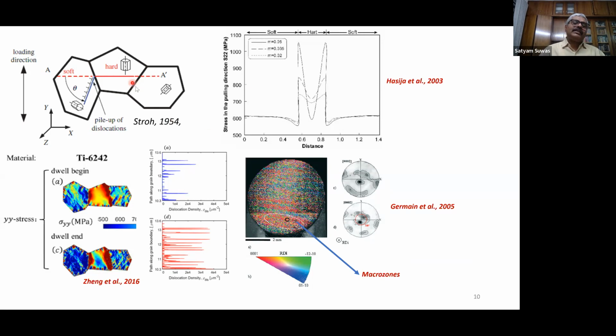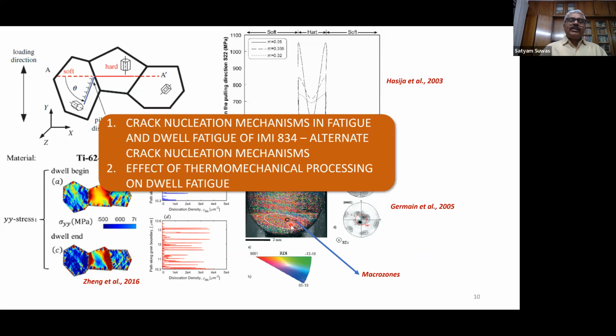So again, this validates the Stroh model: wherever there is a strong basal orientation, and it is also said that the basal grain should be surrounded by non-basal grains. In that case, there will be macrozones forming, and this could lead to a dwell fatigue debit, meaning the propensity of reducing the life under dwell fatigue loading conditions. So these are some of the available knowledge.